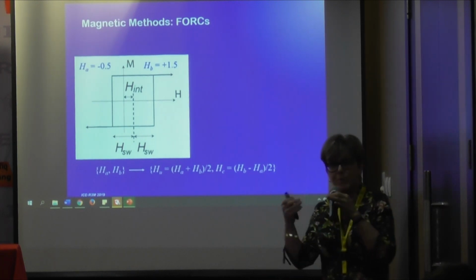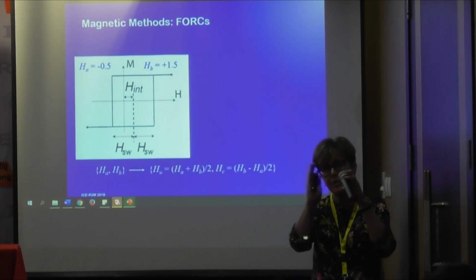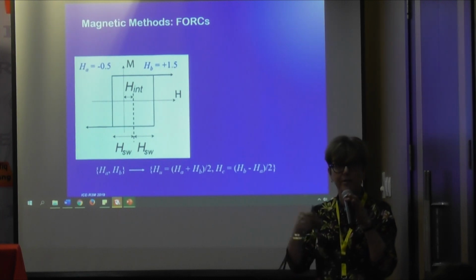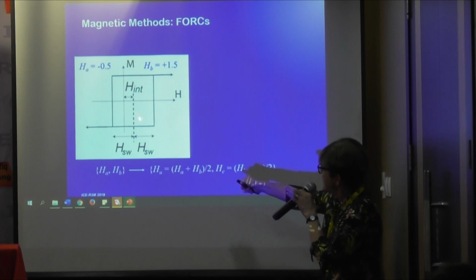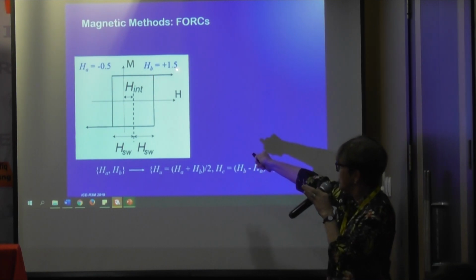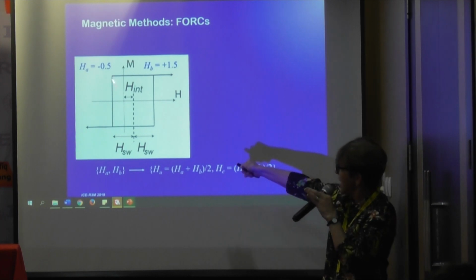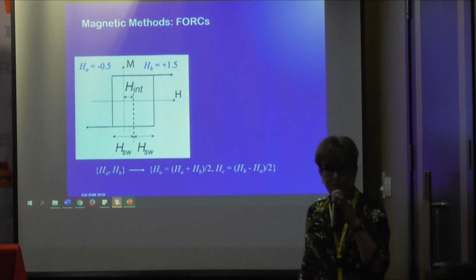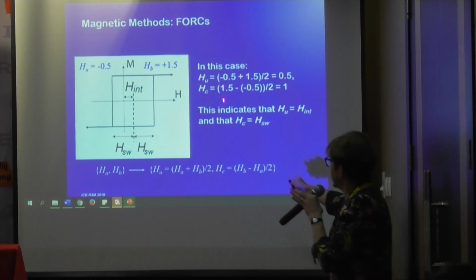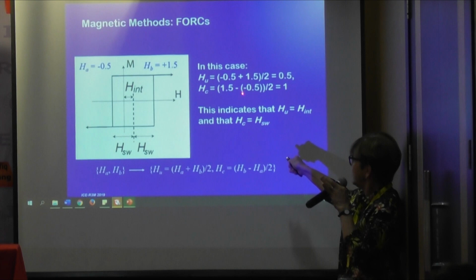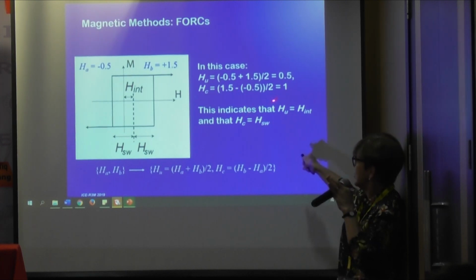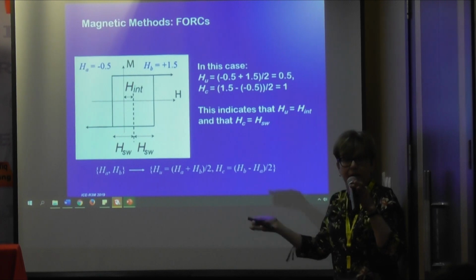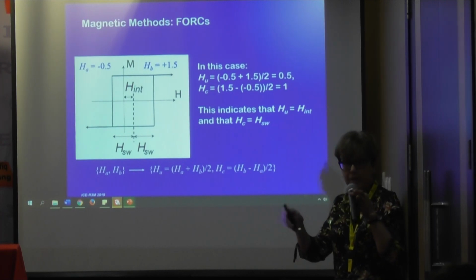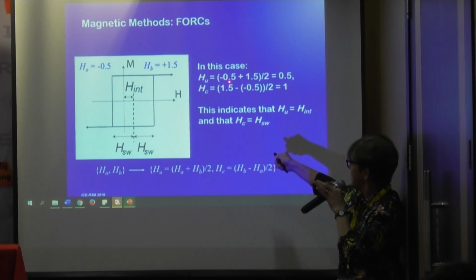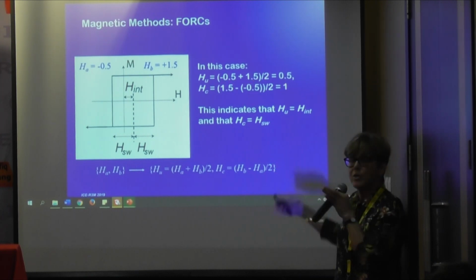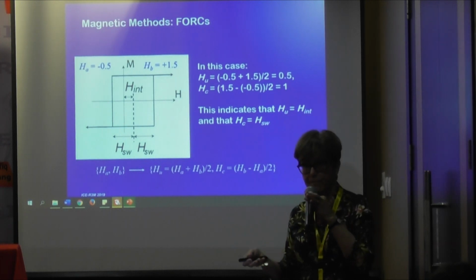Now, when I have interaction between two particles, my loop shifts a little bit, either to the left or to the right, depending on whether the interaction is positive or negative. In this case, I come up here, I switch, but no longer at 1, but at 1.5. And when I come back, I come down at -0.5. So my coercivity is now 1.5 minus 0.5 divided by 2, so my coercivity is still 1. That hasn't changed, it's just my loop is a little bit shifted. But my interaction field now is -0.5 plus 1.5 divided by 2, so now I have an interaction field of 0.5.